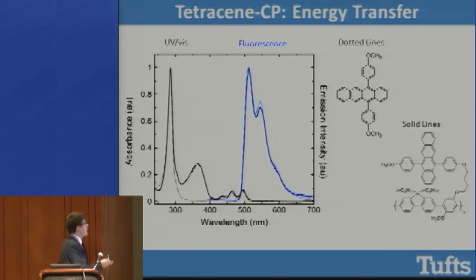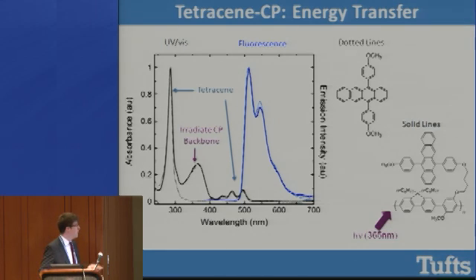In terms of the conjugated polymer, we see that we also have the tetracene units appended to it, and as well we see this very characteristic broad signal between about 300 and 400 nanometers, which corresponds to the conjugated backbone of our conjugated material here. And the nice thing is here, we can very selectively excite at 365 nanometers the conjugated polymer backbone, with well under 5% of the light that we use actually going directly into the tetracene. So when we come in with 365 nanometer light and pump this chromophore here, what we see is that the fluorescence is almost entirely coming out of the tetracene moiety. So what this is consistent with is a FRET or energy transfer process, where light comes into the polymer, transfers its energy downhill energetically to the lower excited state energy tetracene, and very efficient fluorescence comes out of the tetracene moiety. So this is setting up, as compared to the furan derivative, which did electron transfer, this is doing energy transfer before exposure to singlet-oxygen.